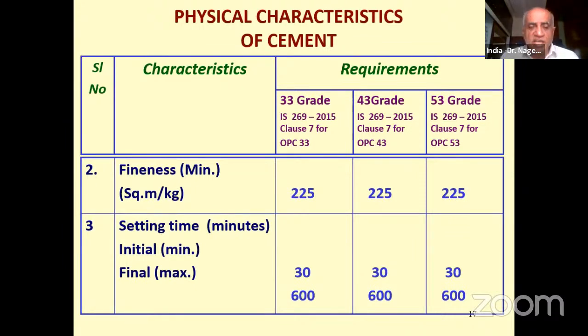Setting time is the one which is really a minimum. Initial setting time required is 30 minutes minimum, and a final setting time is 600 minutes maximum. So if it is less than 30 minutes, we cannot mix the concrete, we cannot transport the concrete, we cannot place the concrete. So there should be a minimum initial setting time, and final setting time shall not be more than 600, because if it is more than 600 minutes, we do not know. It can be any value. So that is an indication that concrete is not at all setting. Even though setting time of cement and setting time of concrete are different, it gives an idea.